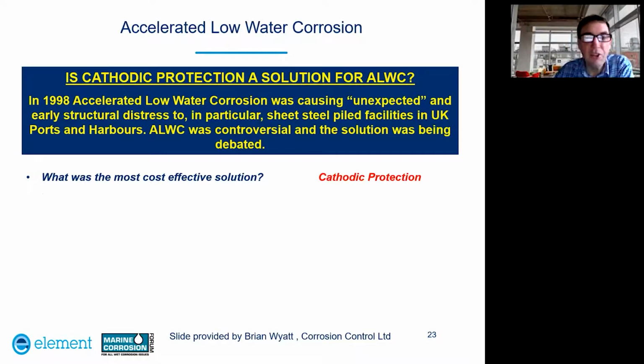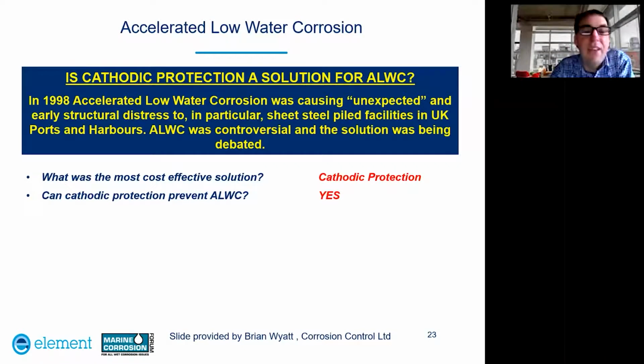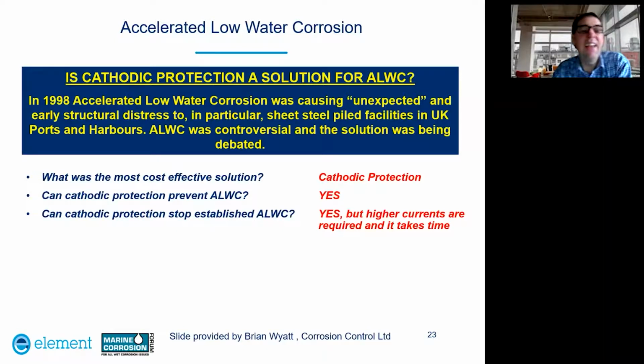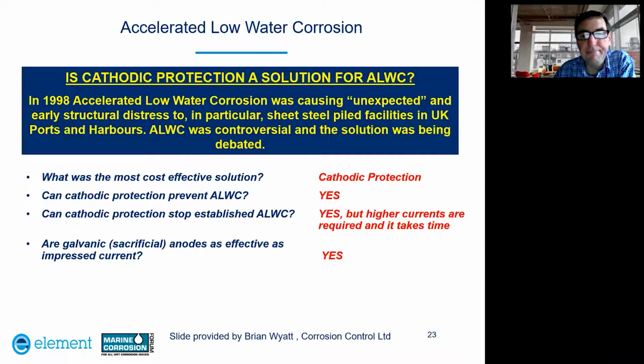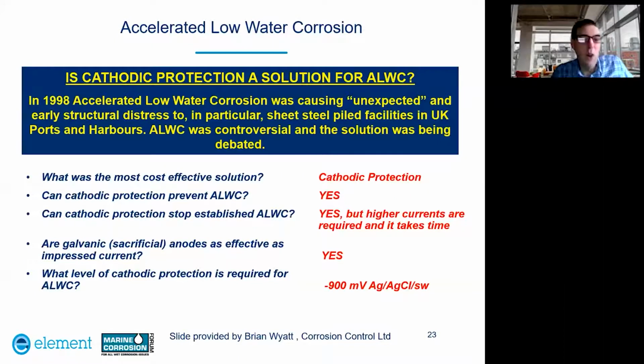And the answer would be cathodic protection. Can cathodic protection prevent ALWC? And the answer would be yes, it can. And can cathodic protection stop any established ALWC? Yes, it can, but higher currents are required and it would take time. And the next question would be, can you use galvanic or sacrificial anodes, and are these as effective as impressed current? The answer to this would be yes. And finally, what level of cathodic protection would be required to prevent ALWC? A potential of minus 900 millivolts against a silver chloride reference electrode would need to be applied to prevent this form of corrosion.